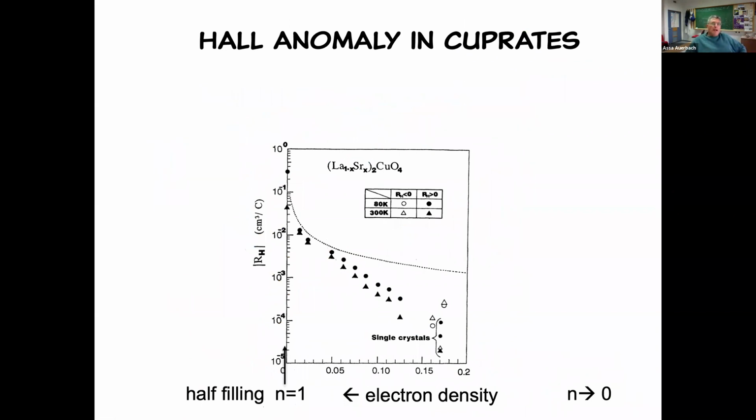Okay, good. So I'm just now going to talk about the other Hall anomaly, which is the Hall anomaly due to strong electron-electron interactions. This is a material which happens to be a high-temperature superconductor, but here I'm not interested in the superconductivity, but in its normal, quote-unquote, normal state behavior of the Hall coefficient as you go towards half filling, and notice that it looks like it diverges like 1 over the distance from half filling, in blatant contradiction to the prediction of band theory or Fermi liquid theory. Fermi liquid theory, even if you tweak it enough to give you the positive sign, because you need to do some changes of the band structure to make the band structure Hall-like in this regime, still it will never diverge as you approach this limit.